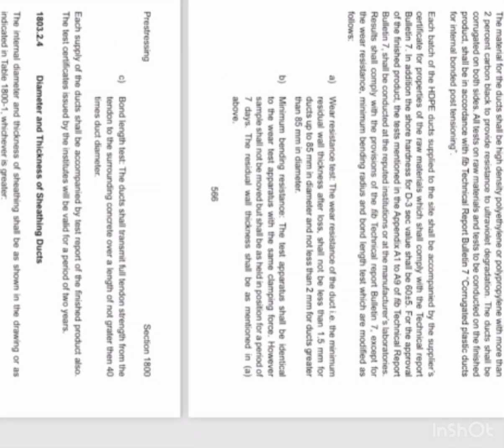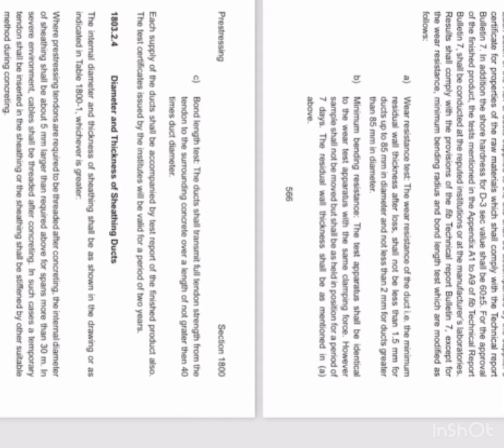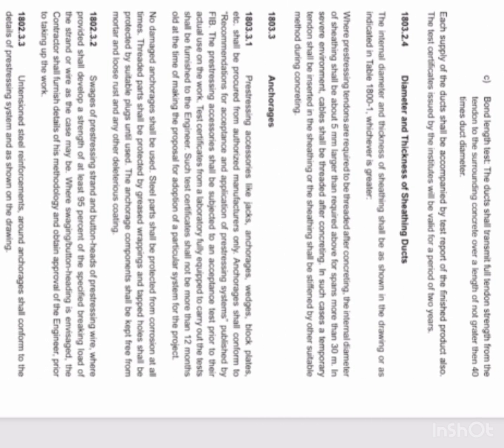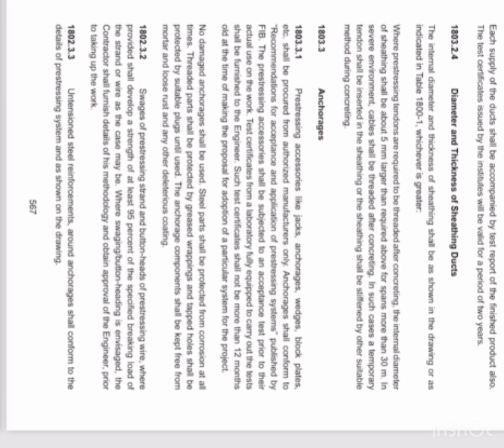Bond length test: The results shall show transmission of full tendon strength from the tendons to the surrounding concrete over a length of not greater than 40 times the duct diameter. Each supply of the duct shall be accompanied by a test report of the finished product. Also, the test certificate issued by the institutes will be valid for a period of 2 years.